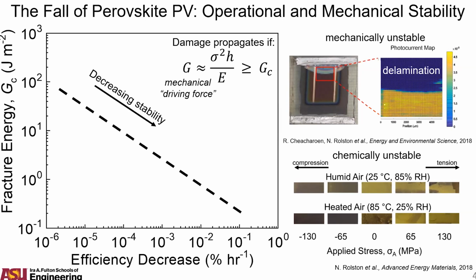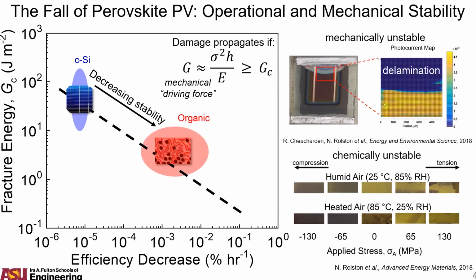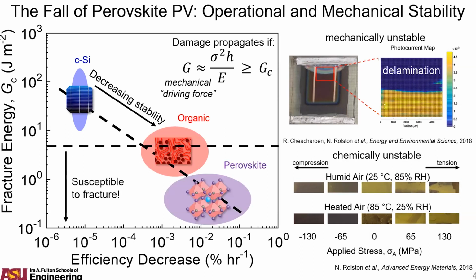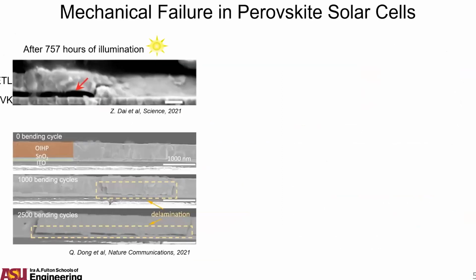So this plot here is showing the fracture energy, the material's inherent toughness, versus stability on a log plot. You want to be up in the upper left-hand corner. That's where conventional technologies are, such as the III-Vs or silicon. Now, silicon can't handle as much in terms of radiation, but at least in terms of heat, humidity, light, and the combinations thereof, it does very well, and it's quite mechanically robust with these strong covalent bonds. Organic PV was a technology that was explored briefly, but didn't make it to market, largely due to mechanical and chemical instabilities. And the real challenge with perovskites is they actually are the most fragile of any PV technology, and also the most unstable. So we're very much studying and trying to understand failure mechanisms in these perovskites and ways to improve on their lifetime.